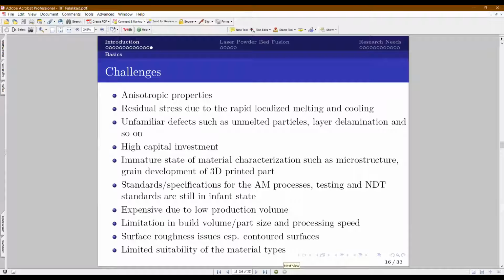Of course, there is a challenge of high cost due to the low production volume or low build rate, and the limitation in build volume. What I understand is that in an EOS machine, you have about 400 by 400 by 400. I don't see any machine which can build a component of 1 meter. Till now, I have not come across one. So there is a limitation in the build volume, and similarly in the build rate or process speed. To build a component of 100 mm by 100 mm by 100 mm takes a few days, whereas in casting or forging it's hardly about an hour to get the final component.